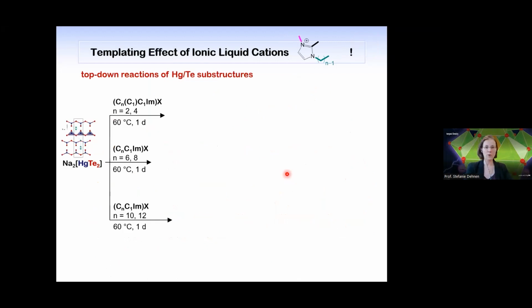This was how it worked. And so we go from tin selenium and germanium selenium to mercury and tellurium. Here, the substructure that we are reacting is not molecular. It's a polymeric strand. And you can see that in this little structure diagram, that we have a zigzag chain of mercury and tellurium. And we react or treat them in ionic liquids, which have the same general structure, but different chain lengths: ethyl group, butyl group, hexyl, octyl, or decyl and dodecyl.